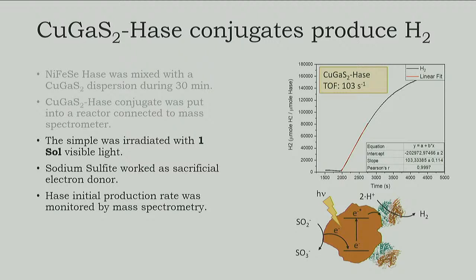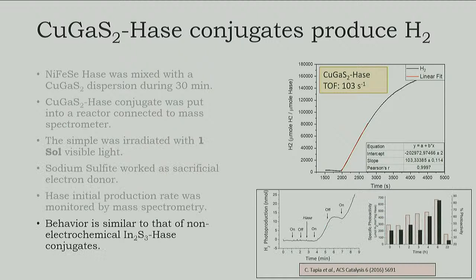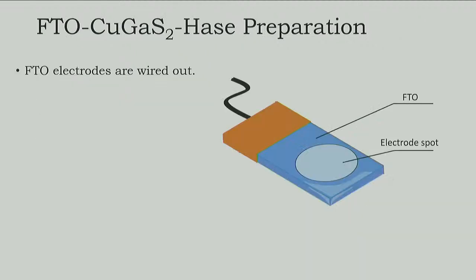With the mass spectrometer, we could also see this hydrogen production. It is lower than the one with indium sulfide, but the irradiation was also lower, because the other one was an early experiment, among the first we did with these illumination reactions. That lamp was working at 450 watts, which is a lot, and now we're working at 80, and of course the production was lower, but the trend is the same. We can see that the production of hydrogen behaves the same way, but it can be immobilized on electrodes.